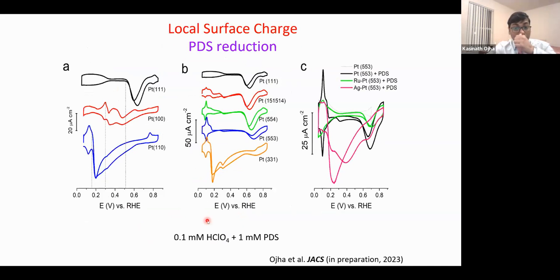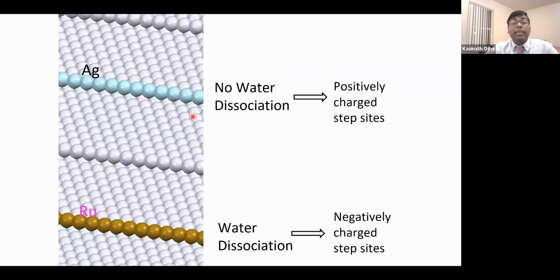I'll not explain these experiments, but the only thing is, silver is not really active at all. So silver doesn't dissociate water, and ruthenium is really active. So ruthenium does dissociate water. Once ruthenium dissociates water, the OH minus adsorbs on these sites. So they are negatively charged, they become negative charge sites. On the other hand, in the case of silver, as it doesn't really dissociate water, those remain as positively charged sites.